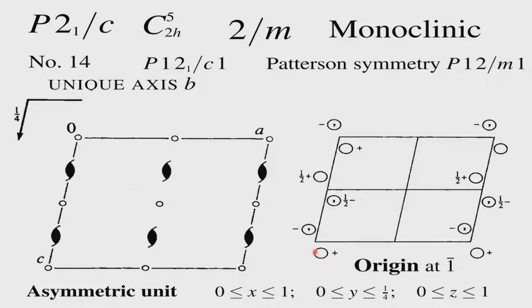It is fairly simple now, very easy, because we see the center of symmetry. So, we know it is a centrosymmetric space group, 2/m symmetry is centrosymmetric. So, we say that this system is centrosymmetric, and we see a 2_1 axis 1/4 removed and a glide plane 1/4 removed. We have understood that whenever there is a translational periodicity involved in a space group, the systems with no translation symmetry, they move by 1/4.